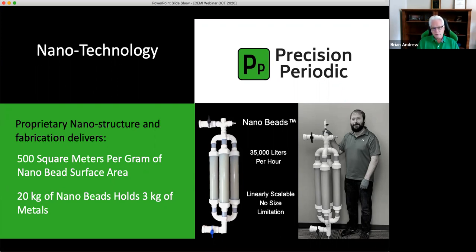The way this filter works is that to pull out every atom of interest from a liquor or a PLS or water, we have to touch every atom of that water. To do that, we have to have huge surface area so that we can let the water run over the beads or over the surface area where we touch every atom. So a sugar cube size, one cubic gram of our material is 500 square meters of surface area. So it's a very, very large surface area for a very small device.